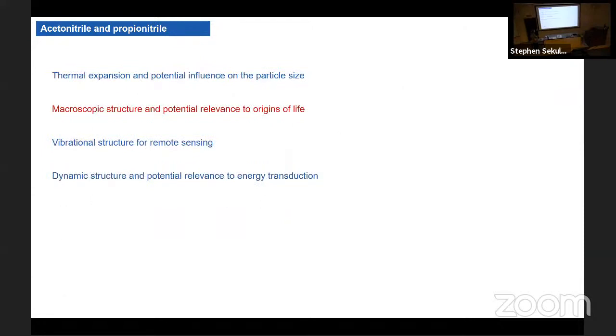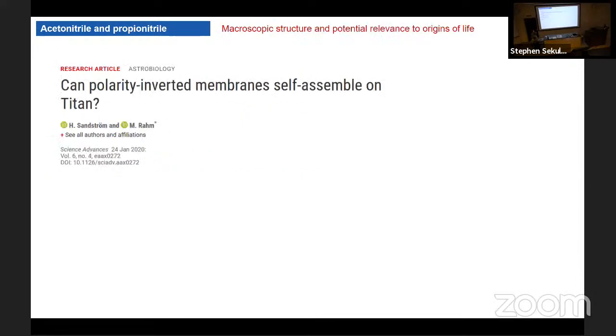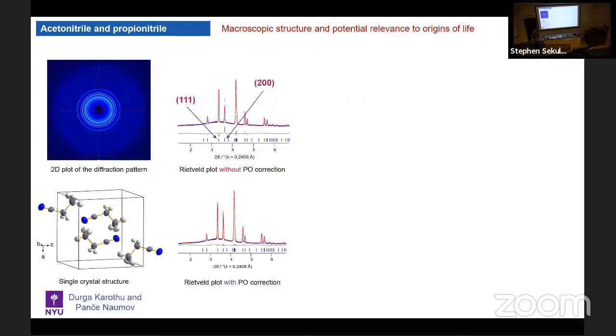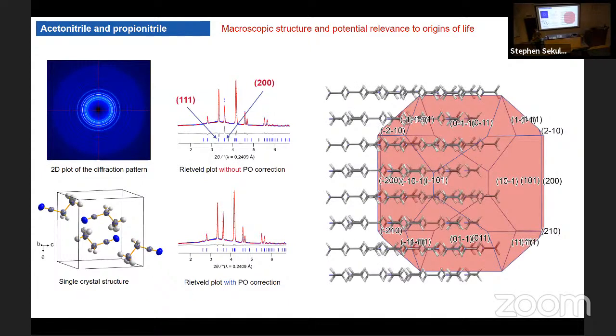Okay, next, the macroscopic structure and how this can be potentially related to life. There is a paper which is quite interesting, it's quite recent: can polarity inverted membranes self-assemble on Titan? So polar structures are important for the origins of life and how these minerals can really help in this direction. Well, I will not go into detail, but we also saw the structure from single crystal, and having combined powder and single crystal together and analyzing the preferred orientation, we can really learn how the crystal will look macroscopically and which facets would be exposed.